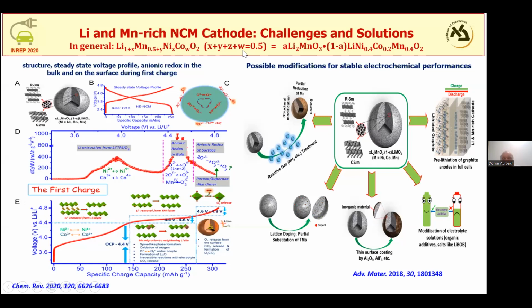And here we have a very interesting situation. It appears that we can reach very high specific capacity. Look, we have here 250, and we can even approach 300 milliampere hour per gram, which is the maximum that can be obtained by intercalation of lithium into transition metal oxide. Here you can see the voltage profiles, and a first process where we activate the material. It appears that whenever we have these materials, we always have at least two phases. When we have a superfluous, extra lithium, we form the Li2MnO3 phase, and the rest is the usual electrochemically active NCM cathode material that works normally.